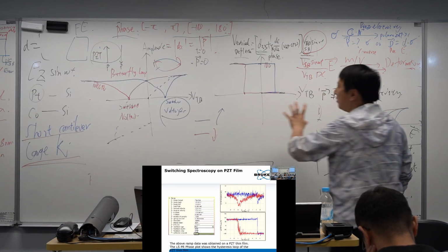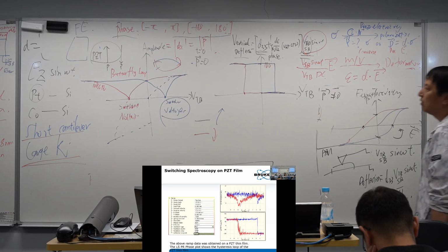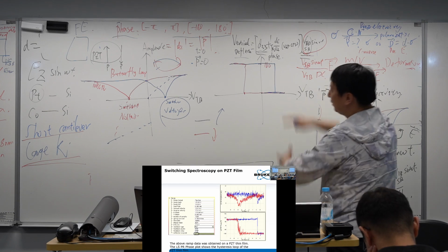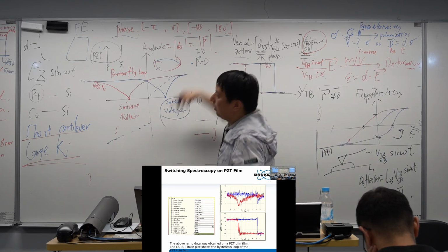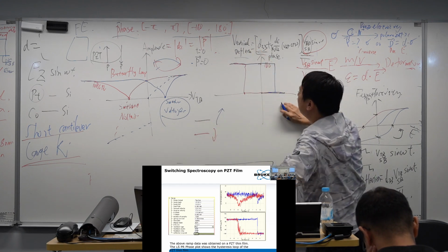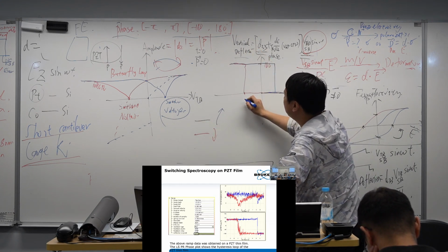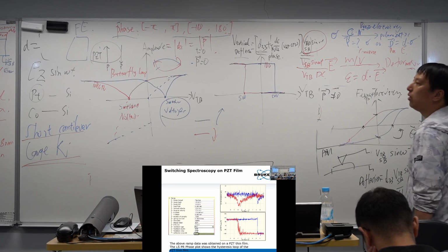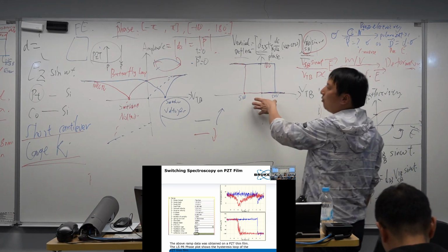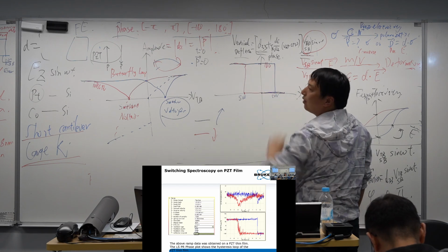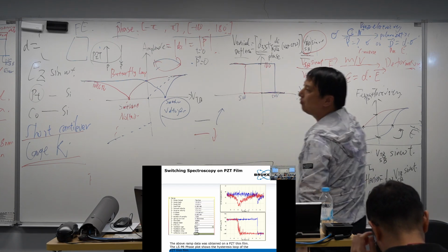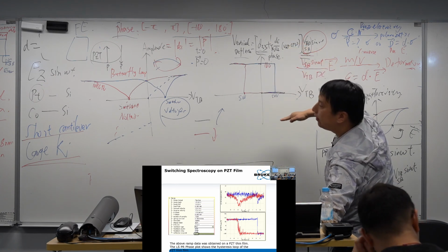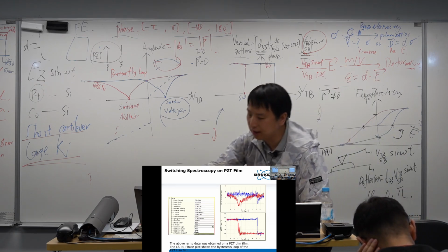So the phase signal is relatively simple. It's kind of square, but the amplitude is kind of butterfly. So from the phase we can get this switching voltage, and this one is another switching voltage. Okay, but as we said, we don't use this kind of setup because we would like to shift the phase. So if we shift the phase lower, then we will get some loops like